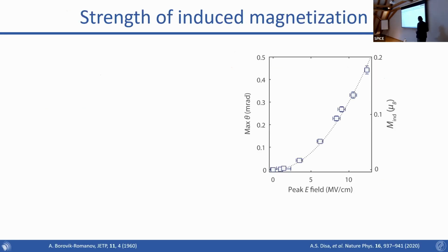The other thing that we can do is now we can see what is the potential, what is the strength of this induced moment, right? So if this is something that's very measurable or it could be useful, or if it's just something fun to do in the lab. And so we can convert in a simple way the rotation angle into the induced magnetization using the magneto-optic constants. And what we get is the maximum that's around 0.2 Bohr magnetons per unit cell. The orbital moment in cobalt fluoride in this case is about 0.5, so it's some significant fraction of that.